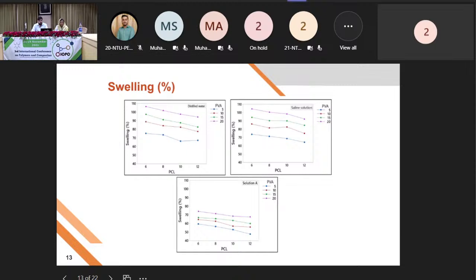Swelling was observed in three different solutions: distilled water, saline solution, and solution A. The results show that with the increase in polyvinyl alcohol levels, the swelling percentages increase in all the different solutions. Regarding PCL, it is also observed that swelling reduces with the increase in polycaprolactone levels.